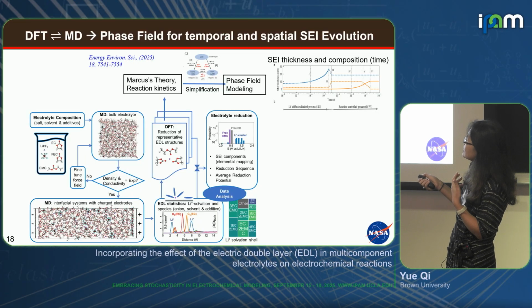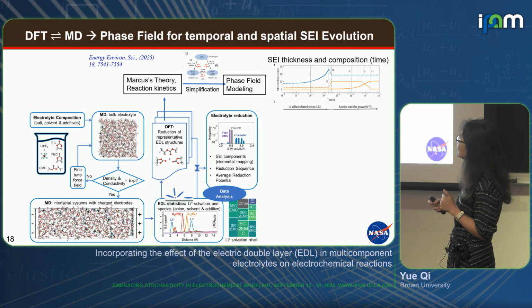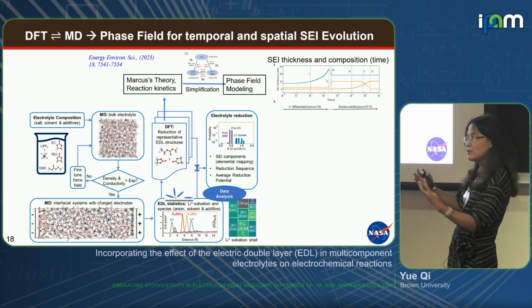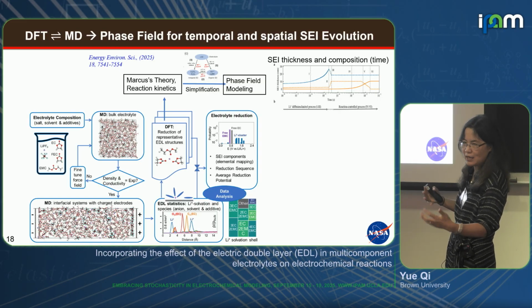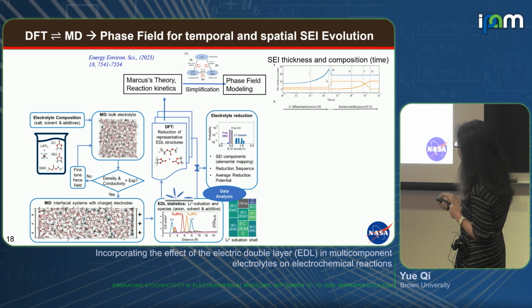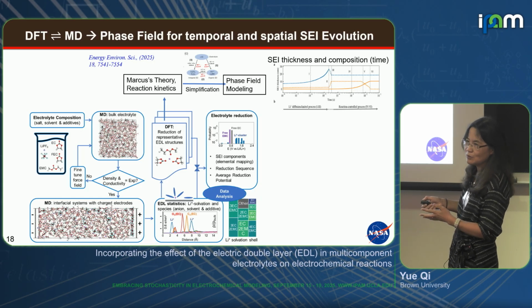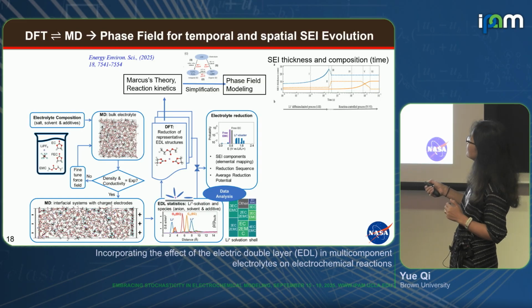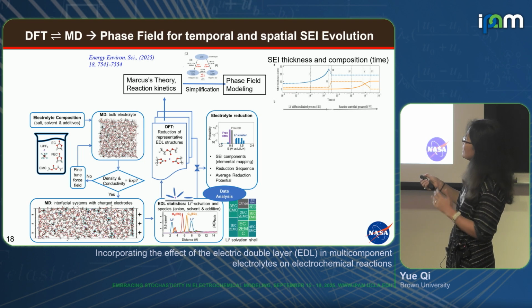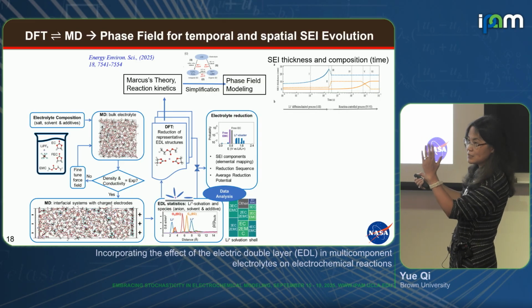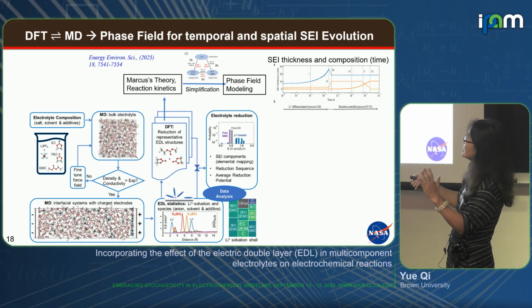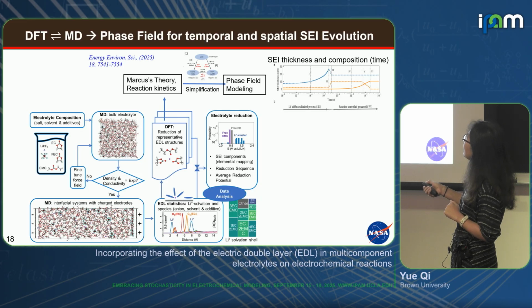And then these are the probabilities of them appearing in this 1 nanometer range. We assume that everything within this 1 nanometer probably has a good chance to get electrons, and that's the electron tunneling distance. And then eventually over time, it's going to be reduced. So we just count these chemical compositions and probabilities this way. This is like a simulated CV, right? So we lower the voltage, and the things that start to decompose and get electrons, you go lower in voltage, more and more can be reduced, right?